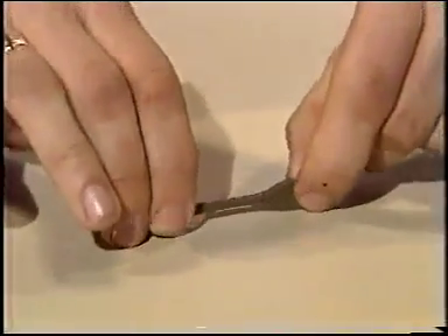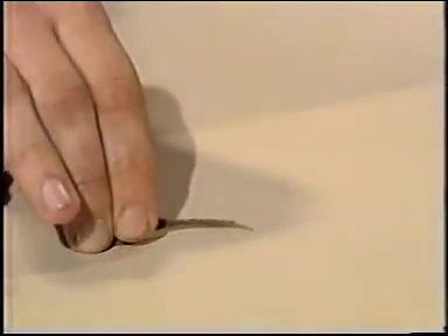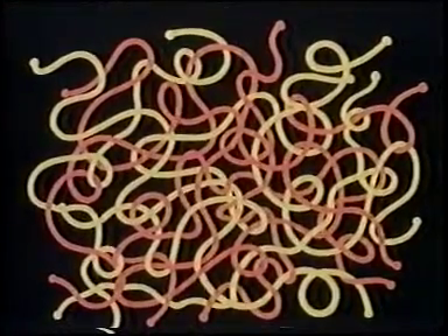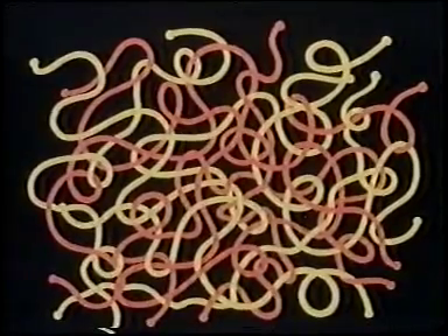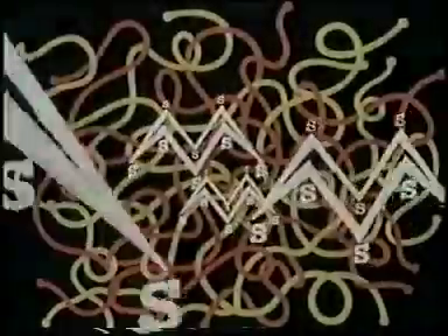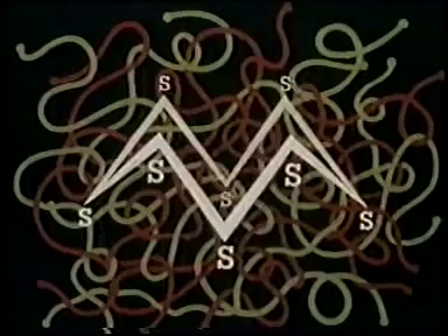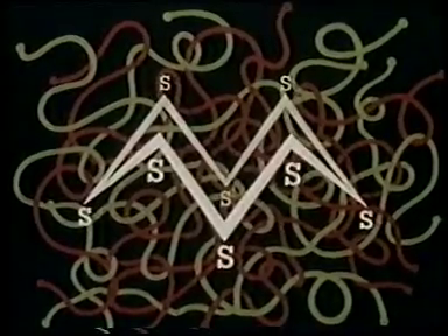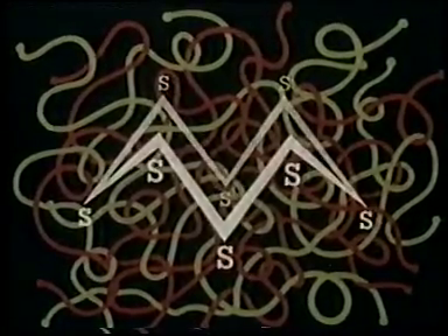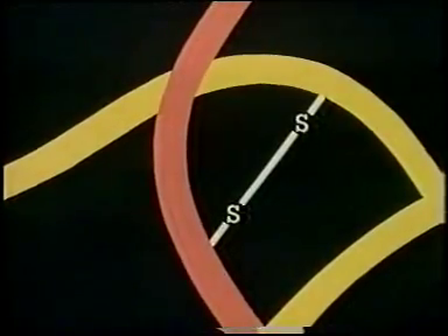Now, here's our sample of SBR before vulcanization. It's soft and weak. And before vulcanization, we can regard the molecular structure as being like a long folded chain. It's a tangled mass and has no resistance to deformation. Sulfur is added to the SBR and the mixture is heated up. The sulfur molecules make rigid bonds between sections of the long SBR molecules, giving them a rigid structure.